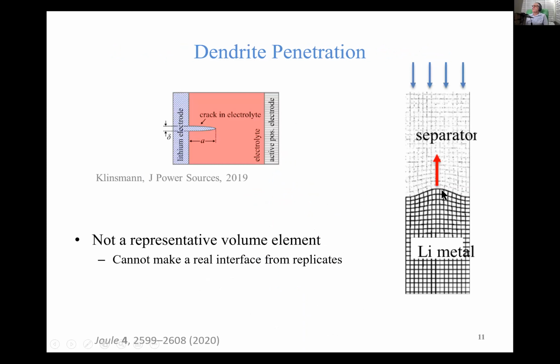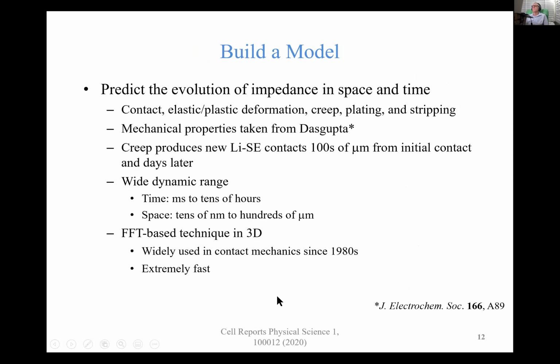And so what this means is that these pictures that are used either in Newman's model or here in Klinsmann's, where you are examining what goes on in a single dendrite, that's perfectly fine, but these are not representative volume elements. And so you can't make a real interface from replicates of these. If you want to do a real surface, you need to consider places where there is no contact.